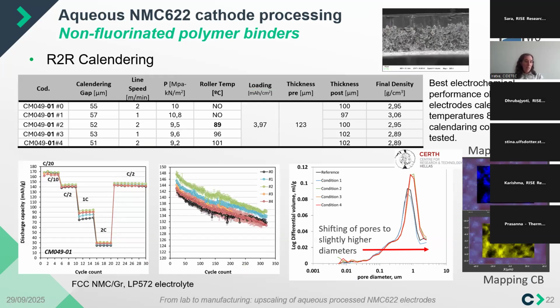And as you see here, all the drying and the porosity arising in the morphology of the coated layer, depending on how you calender, the porosity and tortuosity of these water-based cathodes will also be different, and in a different way than the NMP standard processed electrode. So this has to be adjusted for each particular cathode electrode and waterborne formulation.